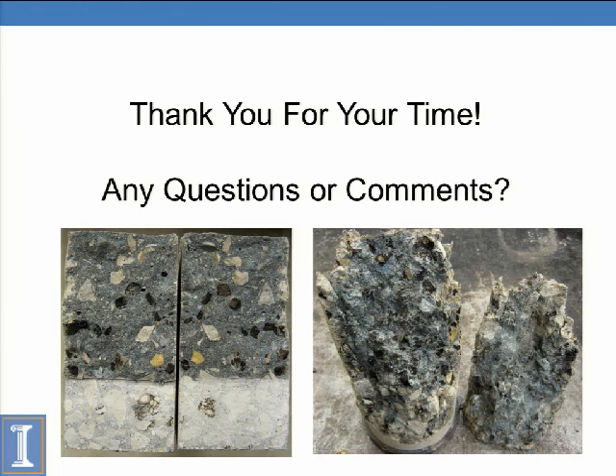I would be kind of skeptical right now with the current state of the FRAP, putting it in the concrete. Certainly we'll be looking at bond improvement studies to try and increase the amount of FRAP we'll add to the concrete. Because of course, if we add more FRAP, we have a much better economy. We're having a more sustainable concrete, more economical concrete. So we want to use more FRAP or more RAP. But as of right now, with the RAP state as it is, I would probably limit it to 50%.